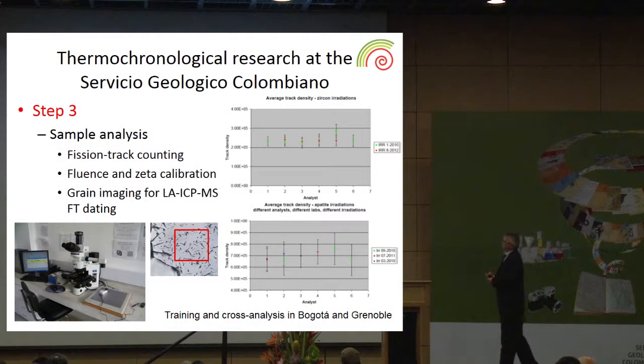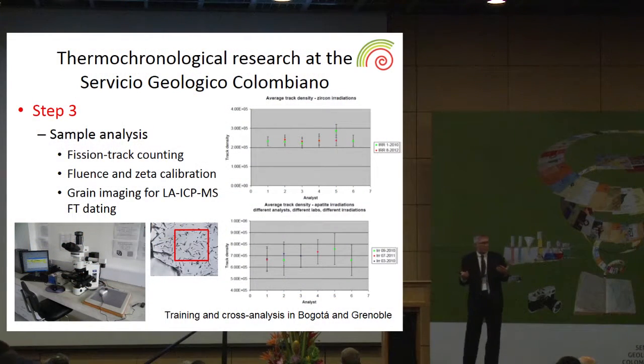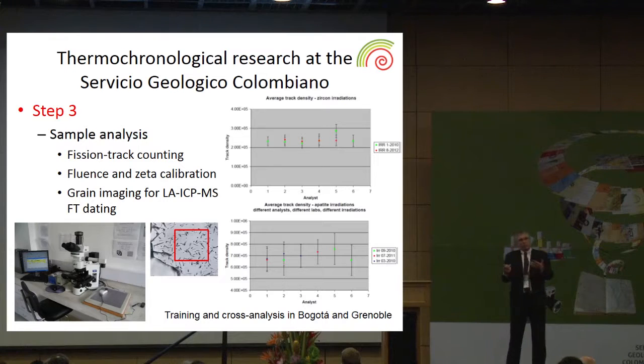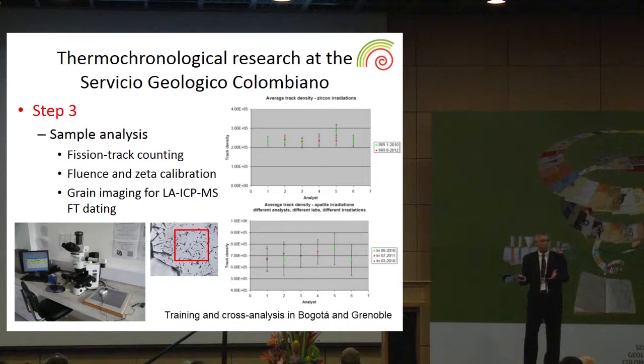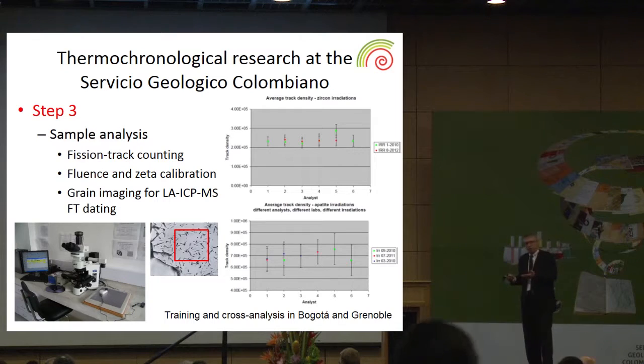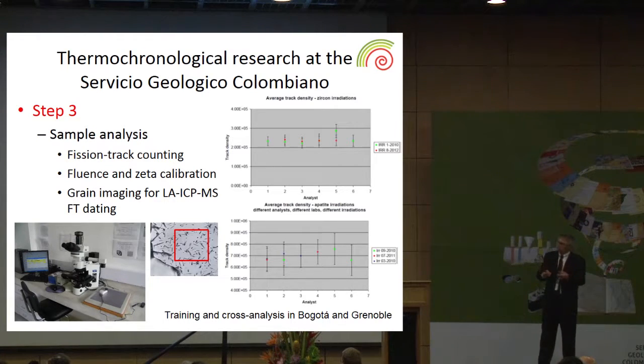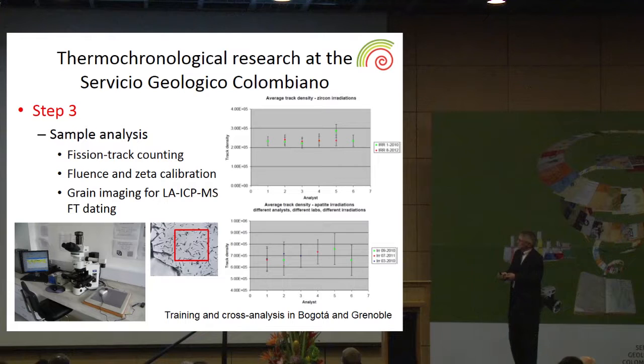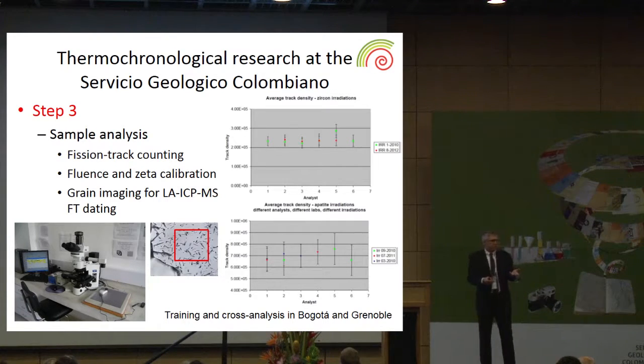So the next step, of course, after we have the samples ready, is to analyze them. And there are two techniques that can be used for fission track analysis. This is the more classical technique, called the external detector method. There the samples are irradiated in a nuclear reactor with thermal neutrons, so we can determine the uranium concentration in the area where we have analyzed the fission tracks. Or we can use a laser ablation ICP-MS system.